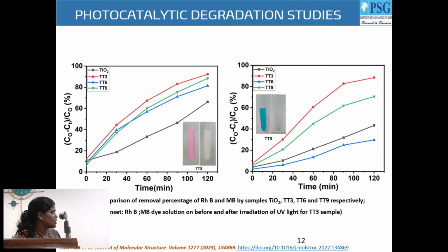with both rhodamine dye and methylene blue dye of the TT3 sample, which shows 97% degradation in rhodamine dye, and with methylene blue it is showing 88 to 89% degradation. And this is the comparison study of both rhodamine and methylene blue with all the composites. In tantalum-doped TiO2, it's showing high efficiency in rhodamine B dye, and in methylene blue it's around 80 to 88%.